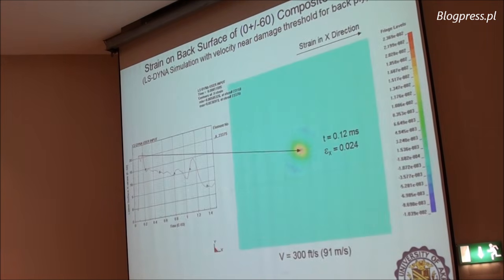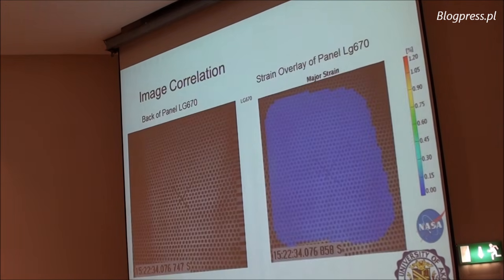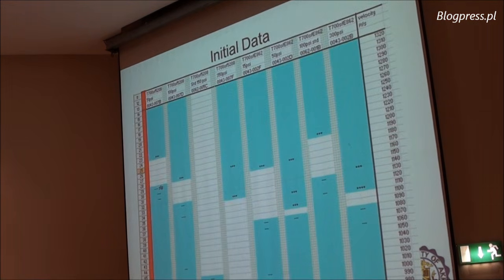therefore saves itself. And it was interesting to me that the common sense would be that if you have thicker material, you have more protection. In fact, in composite, the thinner material, to a certain extent, gives you more protection because it's more elastic, and therefore the damage is not as strong, and that was analyzed through all this analysis. If it fails, of course, because you can always apply force that will fail, the damage is much more localized. It basically breaks and opens the gate, and the projectile flies through, and therefore the damage is not as bad as one would imagine.